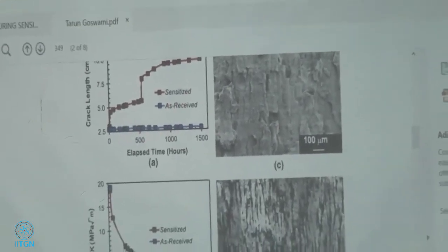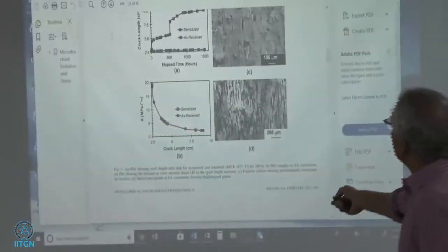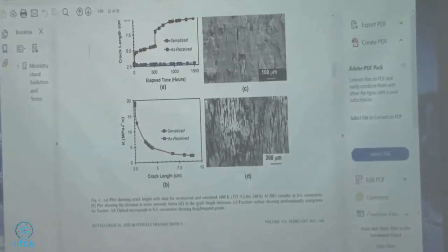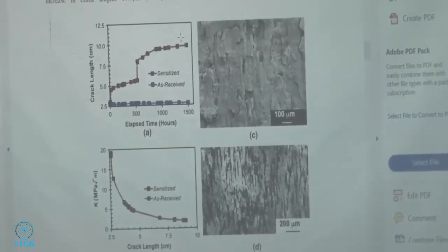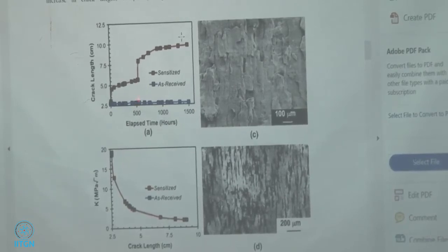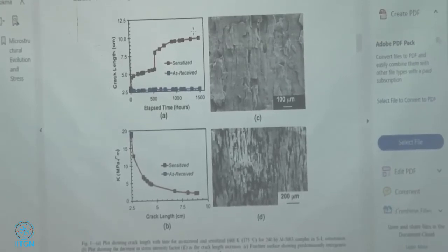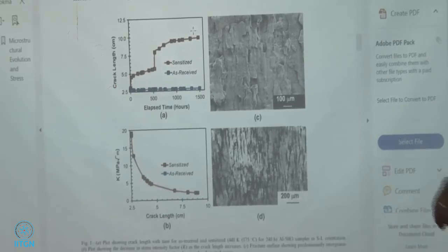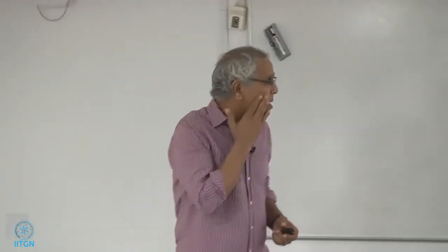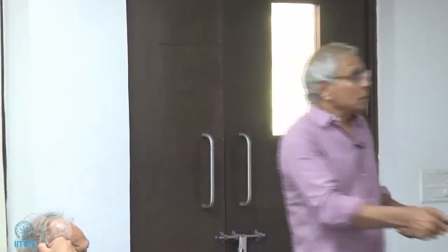In the as received material, that means the material that was not exposed to temperature, the crack length is about 2.5. I don't know what kind of experiments these are, but it doesn't matter. As soon as you have the grain boundary precipitates, because of the sensitization, because of the exposure to temperature, the crack length really goes up. It could be just a specimen with a small crack, could be a dead load type of experiment. Yeah, there are a lot of grain boundary precipitates in the material which are causing a reduction in the ductility. Okay? So the resistance to crack growth has gone down because the grain boundary precipitates are forming here at 175 degrees